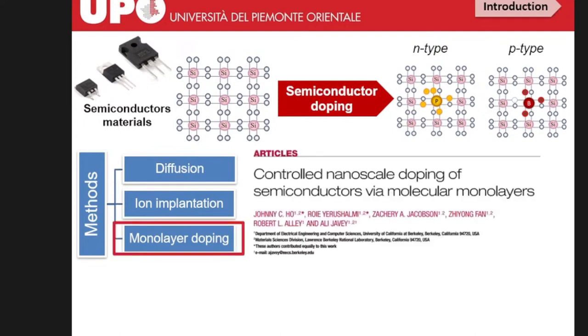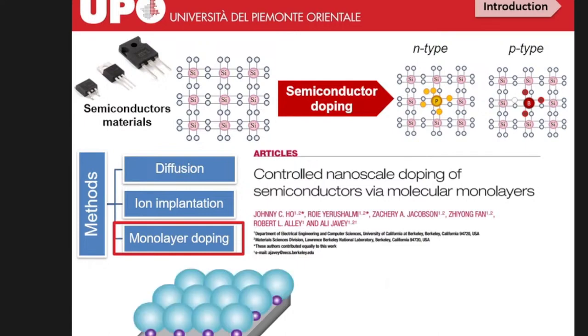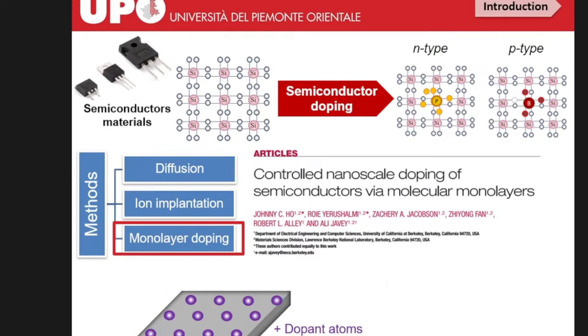The idea of monolayer doping is using some molecules that will act as a carrier for the dopant atoms. So we have a semiconductor and we make a monolayer of these molecules on the surface. After some chemical reactions, it's possible to remove the carrier molecules and the dopant atoms remain on the surface of the semiconductor. This strategy is very interesting because it is controlled and it allows us to move to the nanoscale level of doping of semiconductors.